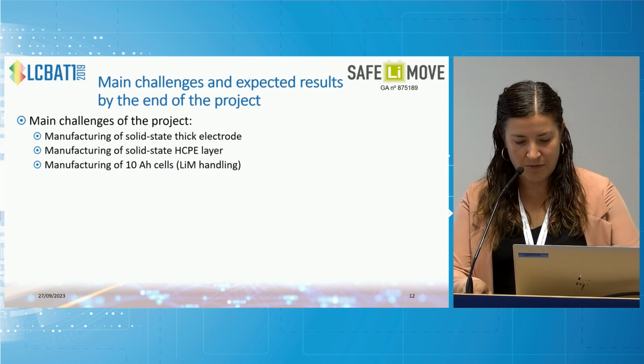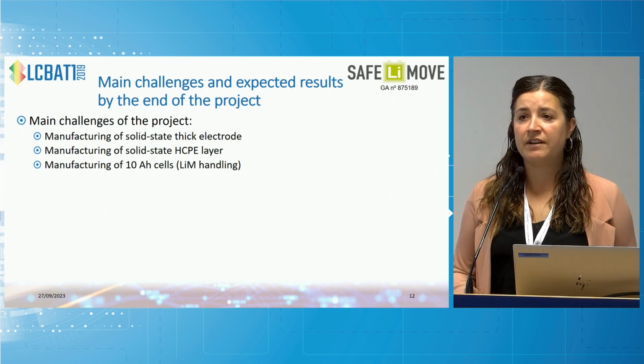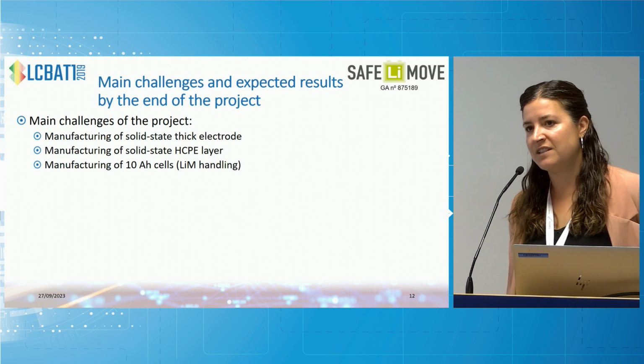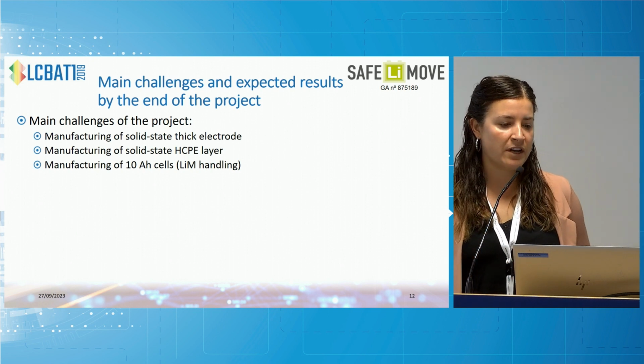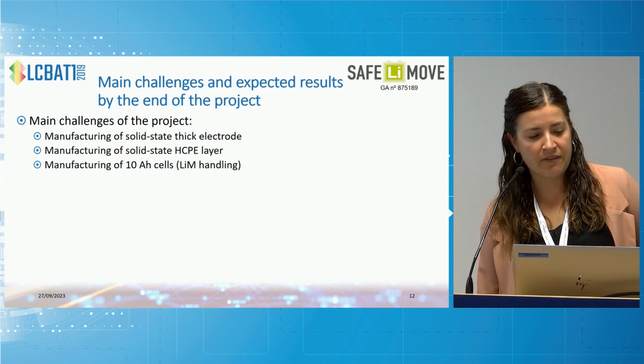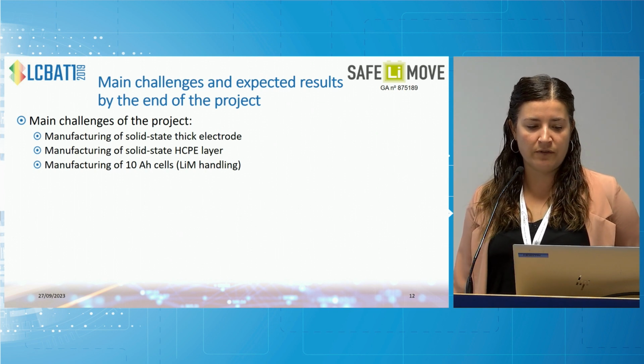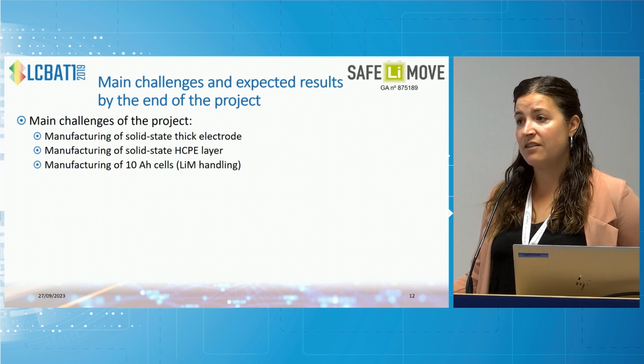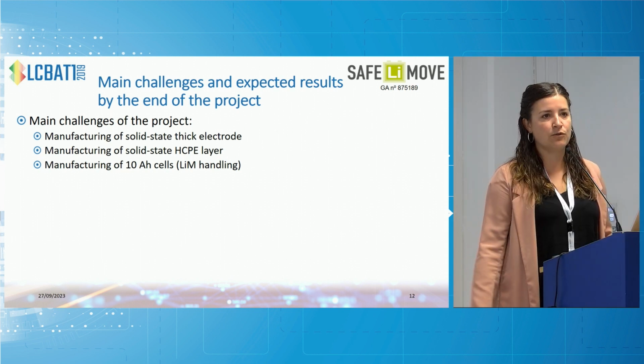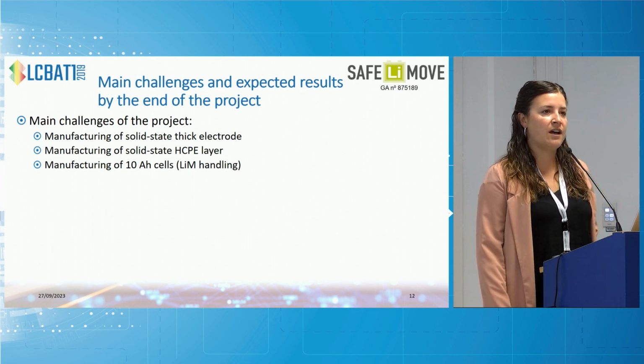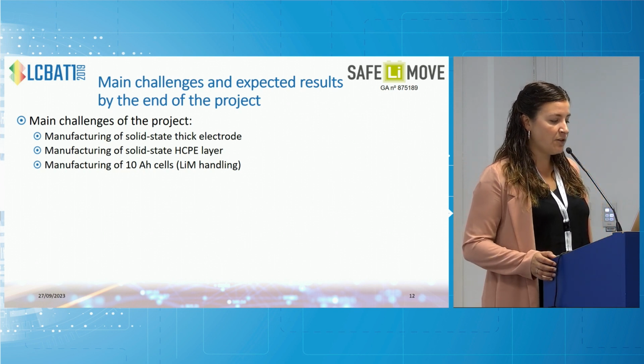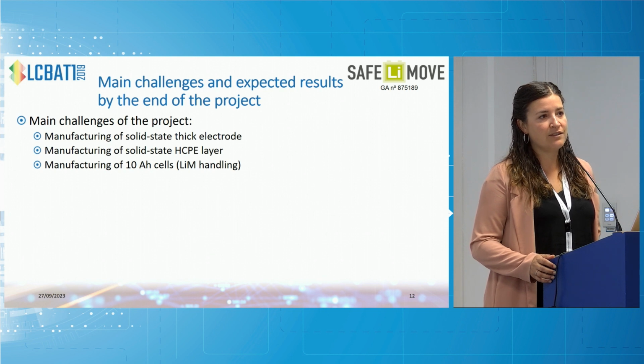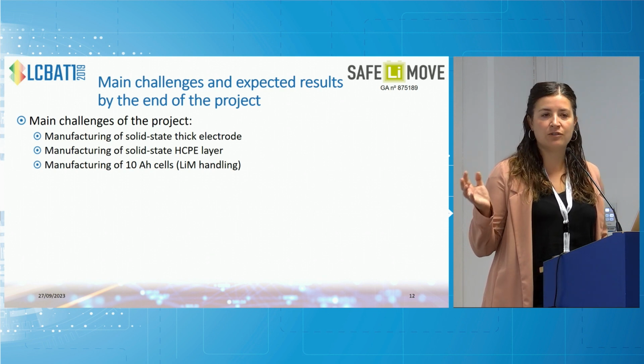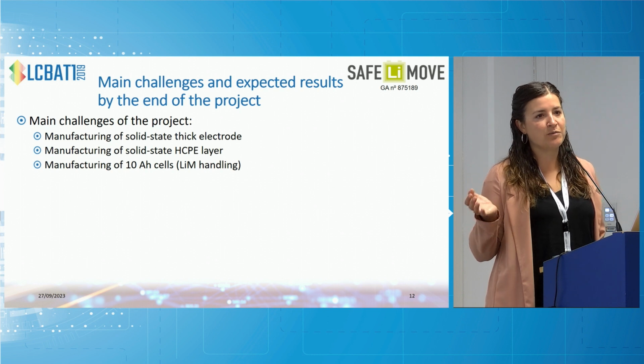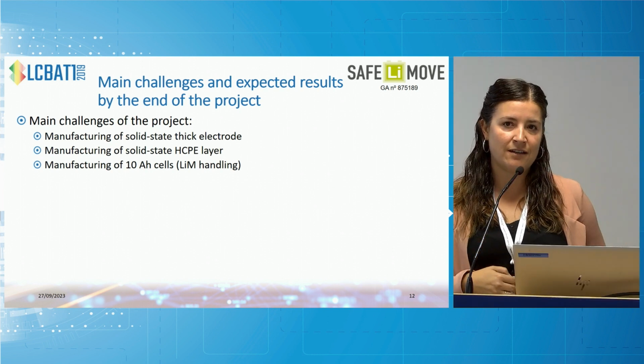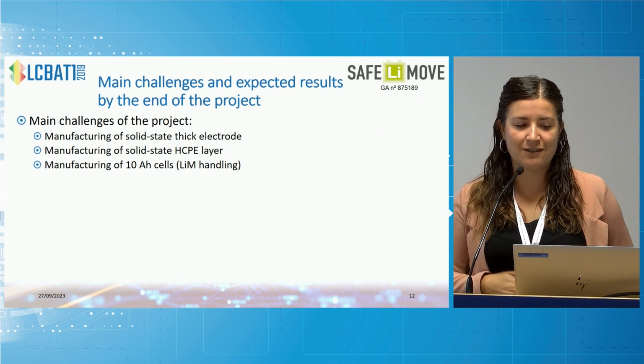And finally, I wanted to summarize the challenges that we have faced during the project. I'm pretty sure that this afternoon, in the topical session related to manufacturing, we will go through this again. We have faced many challenges in the manufacturing of the solid-state thick electrode. It's not really easy to reach these high loadings with good performance. Then there is the manufacturing of the solid-state hybrid electrolyte, balancing ionic conductivity, which usually implies having a quite soft material, but if we translate this into scaling up in a pilot plant, it's not so easy,